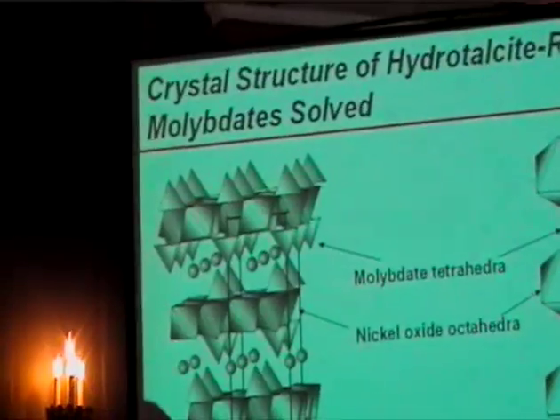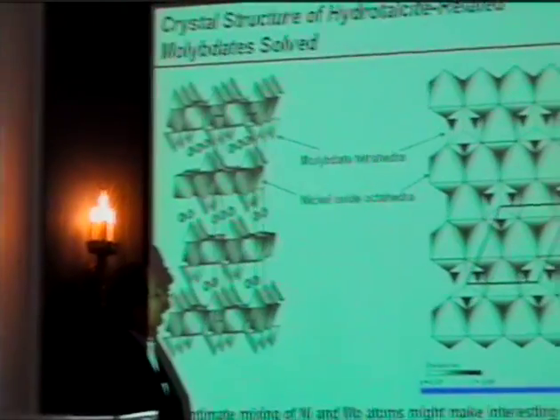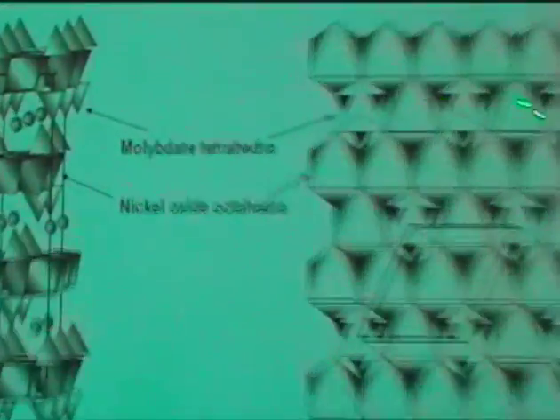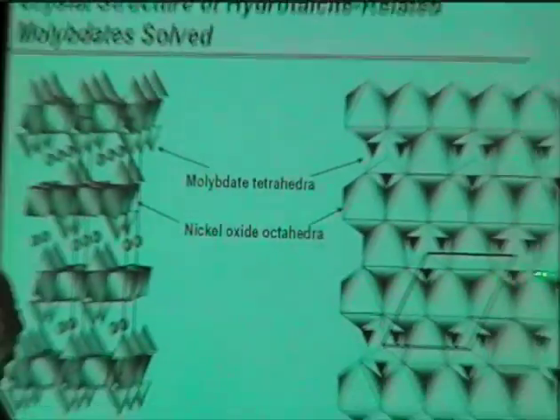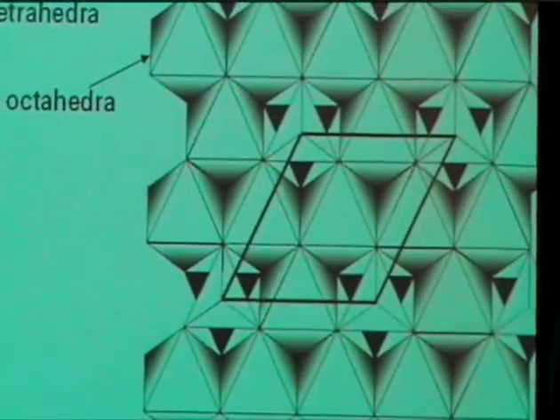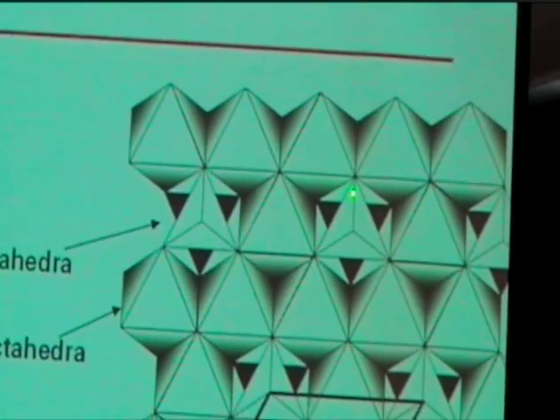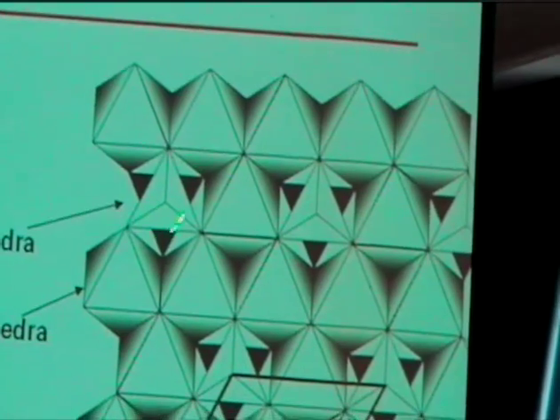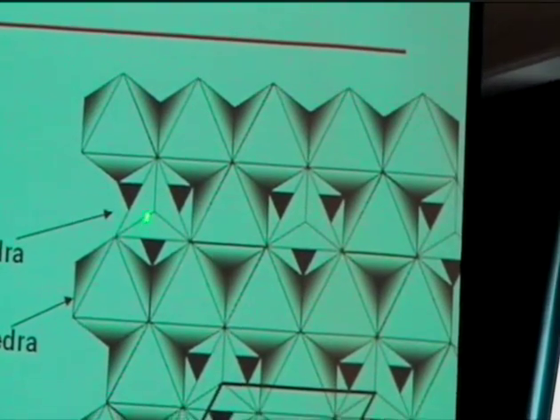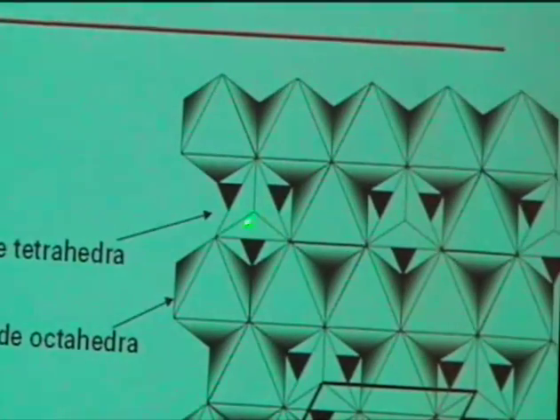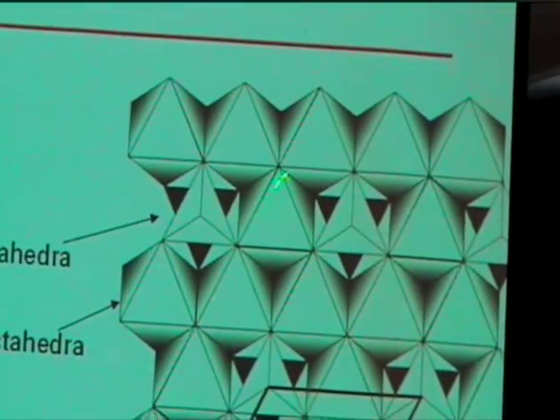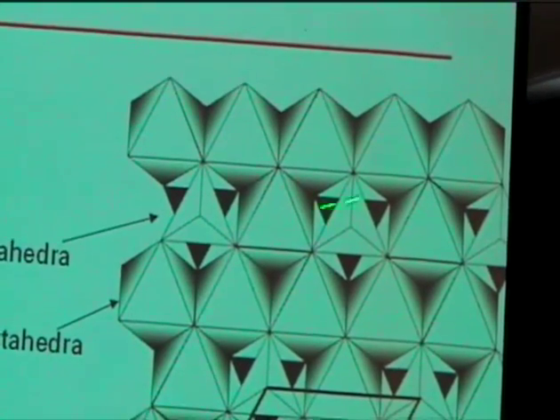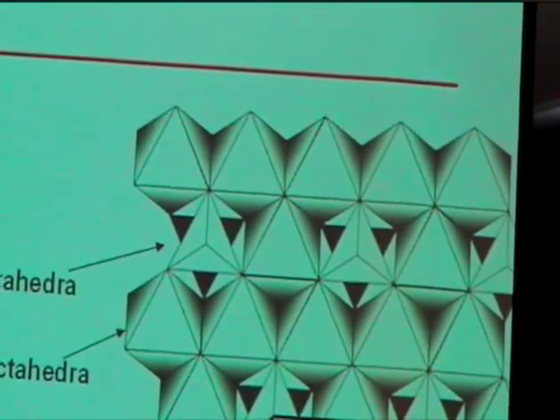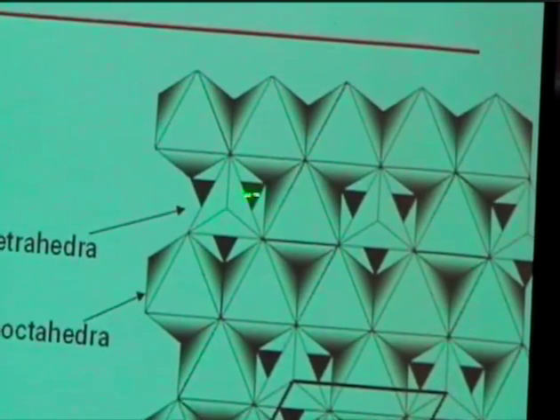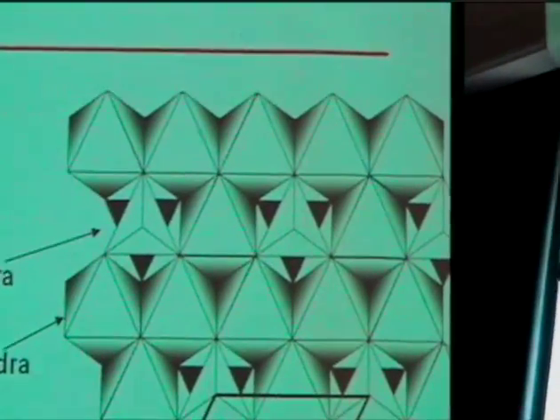These layers that we're having over here contain the nickel, and if this were hydrocalcite, these edge-shared layers would just be filled with more nickel, and if there was aluminum there, there would be aluminum octahedra. Well, what we're finding here is that as we go along, say, the A direction in this way, every other row has a vacancy in there. And above and below the plane of those nickel atoms, we have an isolated tetrahedral of molybdenum. Okay, so now that unit cell is doubling because we're going two rows over before we get the translational periodicity. And it's shrinking along the C direction, which is out here, because now we've got this actually bonded to the sheet. It's not sitting there in this van der Waals space like the carbonate ones.